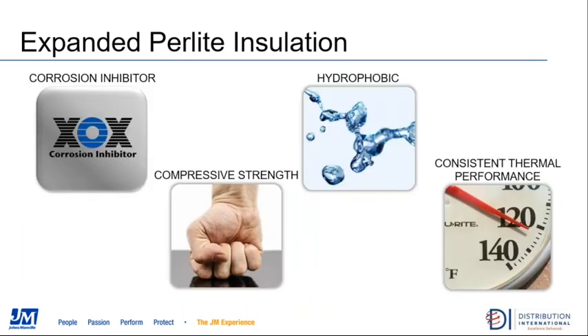Advantages are it's got the corrosion inhibitor. It's got very good compressive strength, not as good as calcium silicate. This is 80 psi, where Thermo 1200 was 100. But this product is more than water resistant. It's hydrophobic, so it'll take more than a 20-minute rainstorm. You can leave it out overnight, 2 days, whatever.